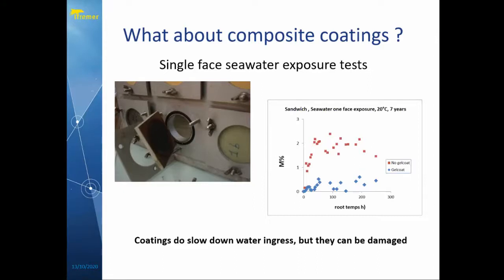We've looked at gel coats, but also anti-fouling paints, erosion coatings. There's a range of layers which you can add to the surface of your blade. But the problem is while they do slow down water ingress, they don't stop it completely, and they can be damaged. So that if you then get the removal of the coating, you get back to your worst case, which is what we're looking at in most of our tests.